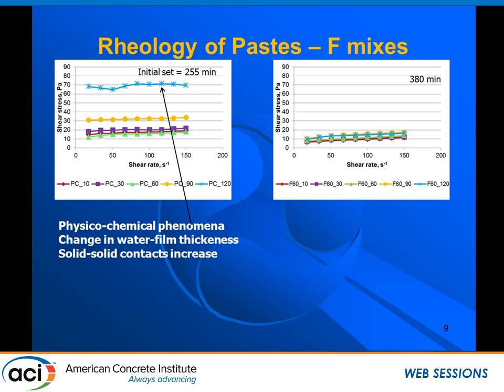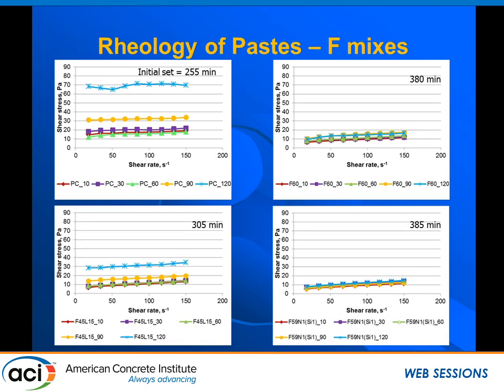For the F fly ash mix, nothing appears to be going on. There is no apparent agglomeration at this point. If we look at the 15% limestone, again we see something happening at least at 120 minutes. For the Nano Silica, nothing is happening.